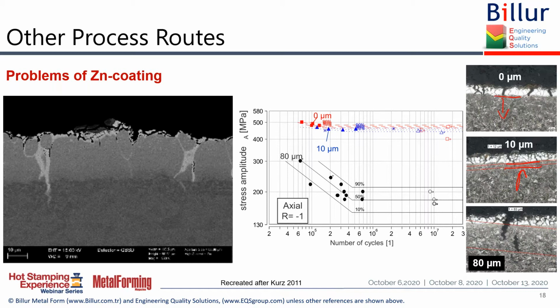But if you have anything over that, then if you take a look at this one, we have less than 200 megapascal as the finite infinite life, whereas here we have more than twice of that. So most OEMs limited their acceptable micro cracks as